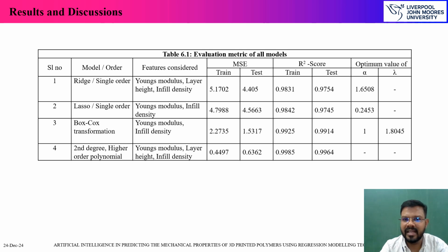Now, moving on to the evaluation stage of these machine learning models that we have used here. The first is the ridge model, which is of a single order polynomial equation. The features considered were three, and then the mean square error for the training and the test data were 5.172 and 4.405, and then the R square value was 98.3% and 97.54%, with the optimal alpha value of 1.6508 for the ridge model.